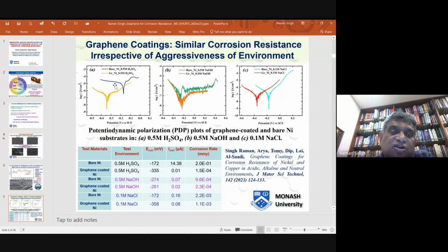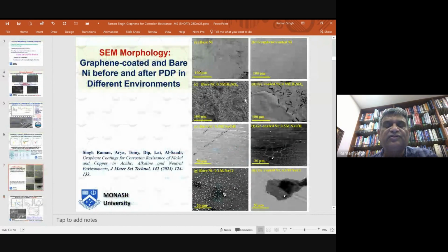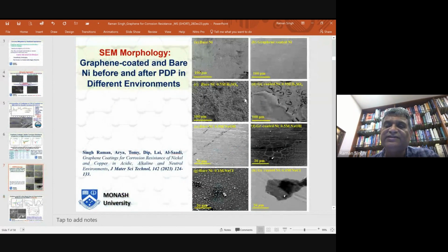Whereas the uncoated one has different behavior. That uncoated one corrodes very, very rapidly in acidic solution. In alkaline solution, it passivates very fast. So that's the behavior, and it is different in sodium chloride solution. So the uncoated nickel behaves differently in different solutions, but the graphene coated one gives the same corrosion resistance. And post-corrosion morphological characterization has given explanations for those.